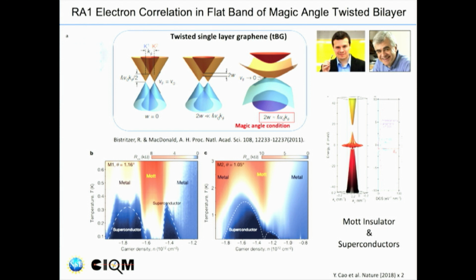But what they found out was two remarkable discoveries, which made two Nature papers last year. One is if you vary the carrier density with the back gate, and then vary the temperature, this is at liquid helium temperatures, when you half fill the band, it actually turns into an insulator. What happens is in that moire pattern the electrons sit on the spots in the moire pattern, they don't talk with each other anymore, and it insulates. And so that was pretty exciting. It's a real insulator, which doesn't conduct very much at all. That was the first paper.